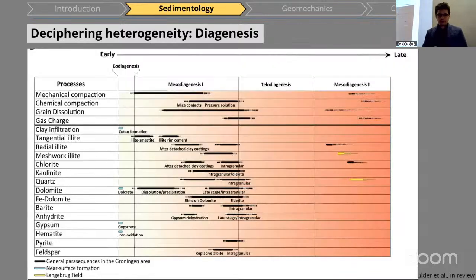Now, there are a lot of these processes. I don't want to go through all of them. I just want to show you there are quite a few clays. So the first, you can see 1, 2, 3, 4, 5, 6 of these processes or phases. They're all clays. So there are a lot of clays involved. But I think very importantly, we also have dolomite, which is more a cement, which forms massively very early on and very strongly cements your sands. So you don't actually have any porosity left. All of these phases are found in nearly all samples.